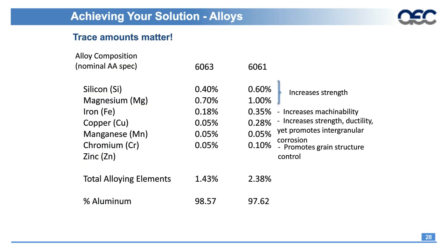So for the most part, you can see that these aluminum alloys, they're over 97% aluminum. Here's 6063 and 6061. There's not a whole lot of difference when you come to the amount of aluminum in something, but these particular alloying elements, the magnesium and the silicon up top here, in 6061, that's where it achieves that strength. So if we go back to where we're talking about how we heat the billets, and then we put the material in solution as it goes through to the extrusion die, and then we quench it. That's where this becomes very important, because that magnesium and silicon become basically combined magnesium silicide within the grain structure or the microstructure of the alloy, and that's where you achieve that strength.